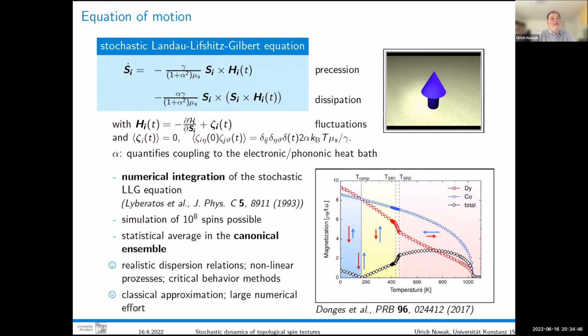If you do that all properly, what happens is that you simulate a multi-spin system in the canonical ensemble. That means in a heat bath. So there is a heat bath that defines a temperature T, and your spin model is in that heat bath. And all properties that you can calculate, the time average of them converges to statistical averages in the canonical ensemble. So in other words, you can calculate dynamic properties, magnons, thermodynamic properties, thermal properties, phase transitions, and things like that.